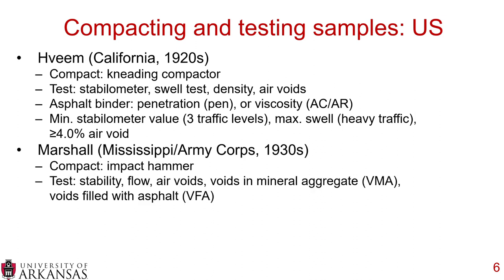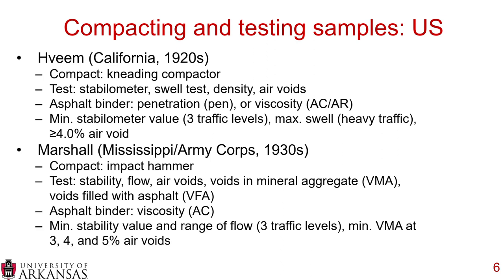The Marshall mix design procedure came out of both the state of Mississippi and the Army Corps of Engineers in the 1930s, and you compact samples using an impact hammer. The tests that you run include stability, the Marshall flow, air voids, voids in mineral aggregate, VMA, and voids filled with asphalt, VFA. The asphalt binder, you use the viscosity grade. You do not use the aged version, just the AC viscosity. And you're looking for a minimum stability value and range of flow, again at three traffic levels, and a minimum VMA at 3, 4, and 5% air voids.